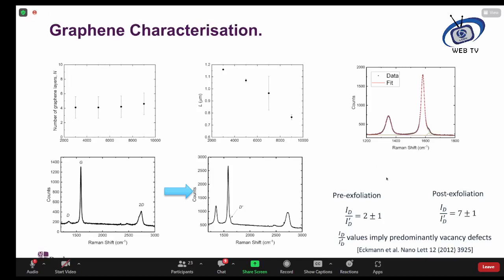And finally, we can determine the nature of the defects within the graphene as well by looking at the Raman spectra, fitting them carefully and taking the ratio of this peak here, known as D primed, to the D peak. And we find from this ratio that we predominantly have vacancy defects within the few-layer graphene that we produce by shear exfoliation. So we take the shear exfoliated material, we vacuum filter it to produce freestanding binder-free electrodes